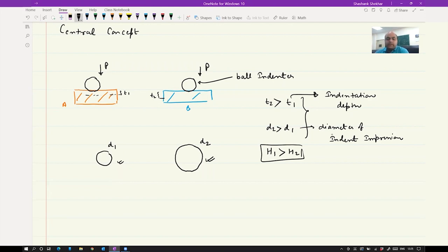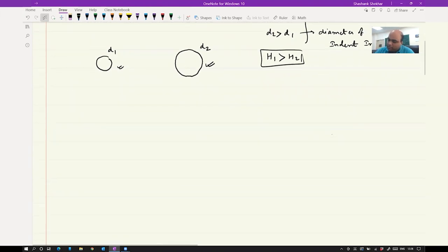Okay. So this is a central concept of indentation hardness, that we try to see the impression. Right? What is the impression of the indent you have made? Okay. But in Rockwell, we don't see the impression. We measure the depth of the indentation. So in Rockwell, we use the concept of say T2 greater than T1. And in other Brinell and Vickers, we see the indent impression and then measure the diagonal length or say diameter of the circle, which is the indent impression, and then finally we measure the hardness. Okay, so this is the central concept of indentation hardness. So in general, the hardness we can write as load by indentation area.